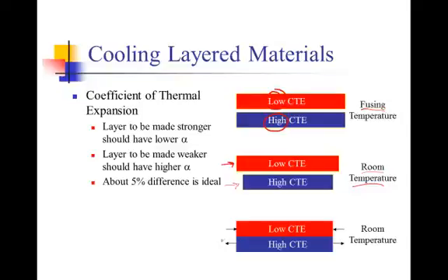And so they will cool down to an intermediate size, and the one that wanted to shrink more, the one on the interior with the high coefficient of thermal expansion, is being stretched. It would like to be smaller than it is. So it has a tensile residual force placed in it. And the one that did not want to shrink as much has a low coefficient of thermal expansion. It is being compressed by the high CTE layer to be smaller than it wants to be. And so it has a compressive residual stress that squeezes cracks closed on the surface.